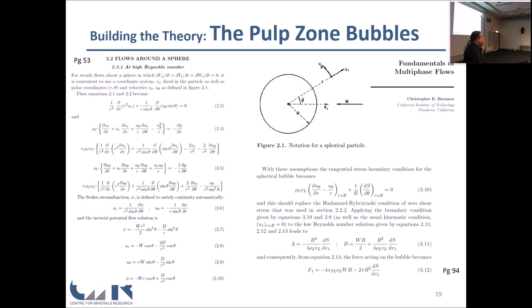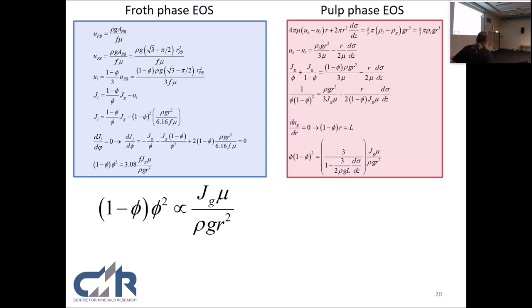And I'm going to tell you that surface tension gradient is what all the solids roll up that and out of the cell. It's a few hundred nanojoules per square meter, and it can lift 10 tons an hour, no problem, because there are millions and millions and millions of bubbles. It's the power of surface energy. So this is actually truly nanotechnology in that sense. We add a very small amount of frother, and that's all that's required, and the frother does that job. The frother addition is so small that we can't detect it when we measure surface tension change, and yet we can lift 5, 10 tons an hour. Isn't that remarkable? How do you eat an elephant? One bite at a time. Well, that's how flotation cells churn out rocks, one particle at a time. So that's core to the model that I'm going to show you.